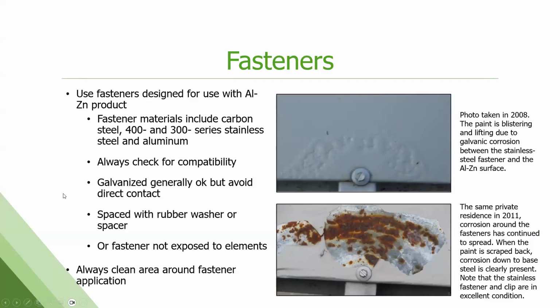So galvanic corrosion, this is a stainless steel fastener that was used on a painted Galvalume roof that's 300 feet off the surf break in Southern California. This complaint always comes in as my paint is bubbling and failing. Well, yeah, your paint's failing because the metal is rusting from the inside out and has nothing to stick to anymore. So you can see that around this stainless steel fastener, there's also a stainless steel support member with a stainless steel gutter that's attached.